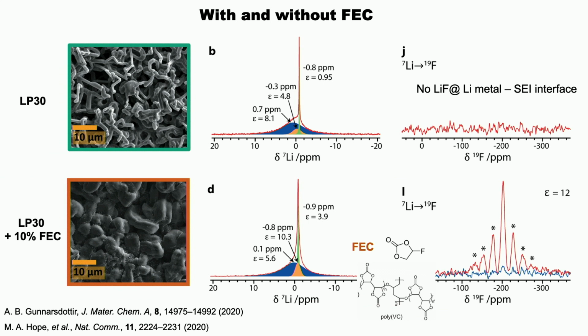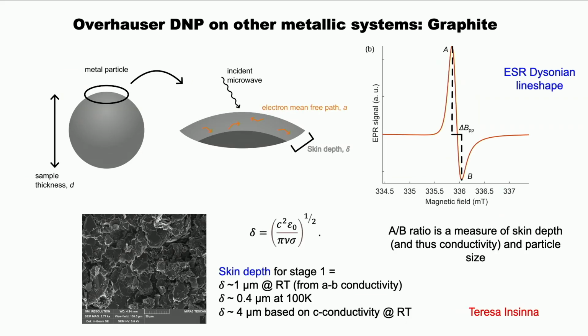And so in this experiment, we transferred the polarization, we enhanced the lithium signal, and then we transferred it to the fluorine. And surprisingly, there was no lithium fluoride. And the lithium fluoride has been thought to be the major critical component of the SEI, but there isn't any. But if you add an additive like FEC, which is this fluorinated carbonate, then lo and behold, you have some lithium fluoride. So then just to end, well, what about graphite?